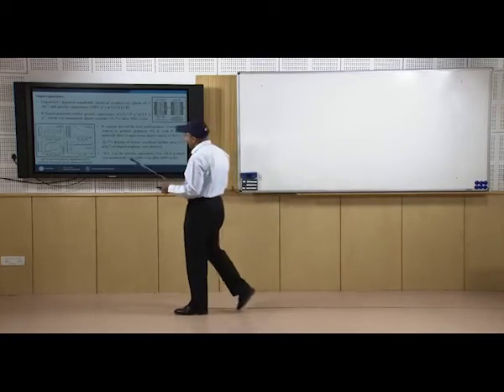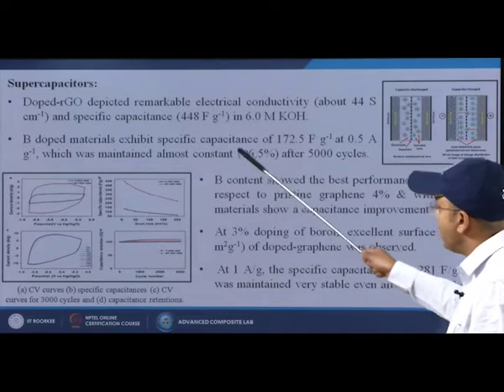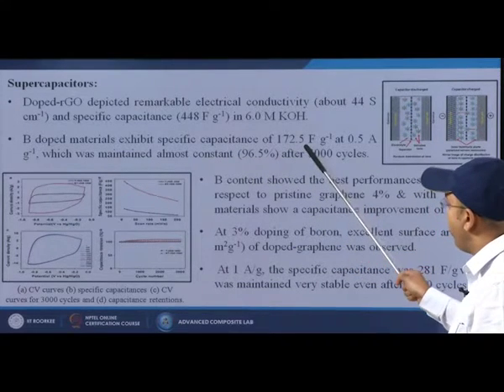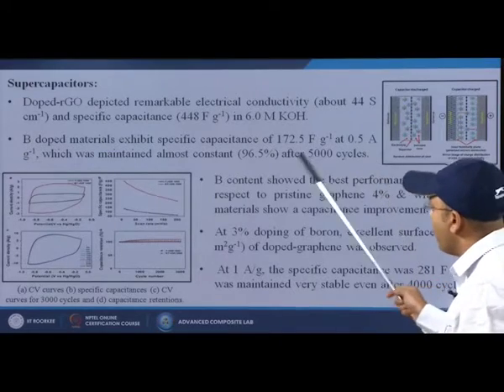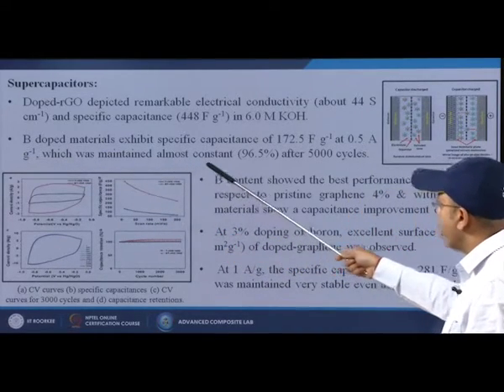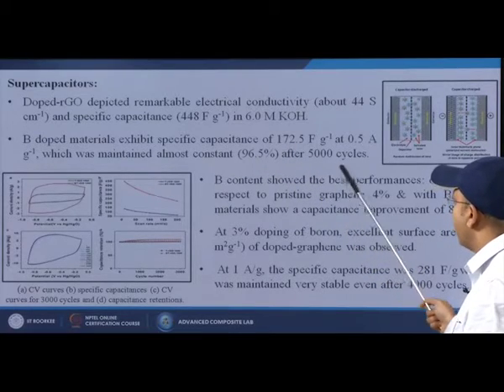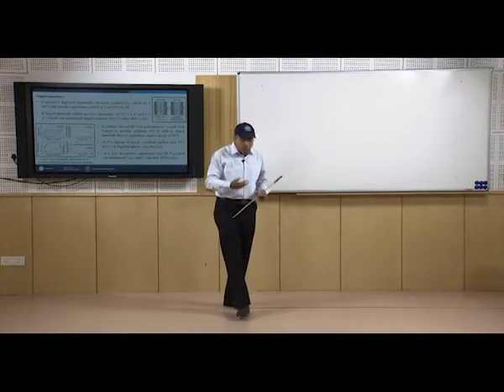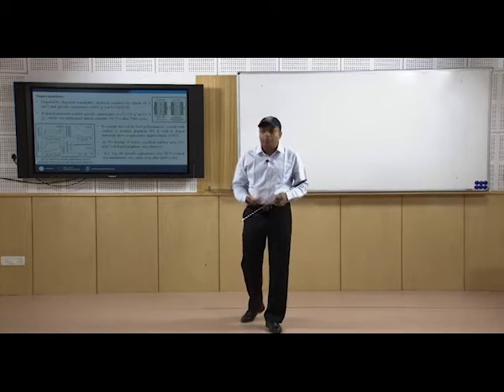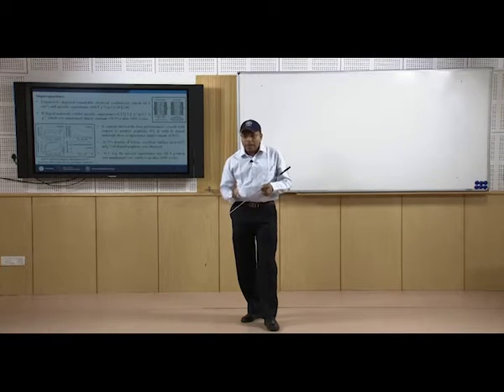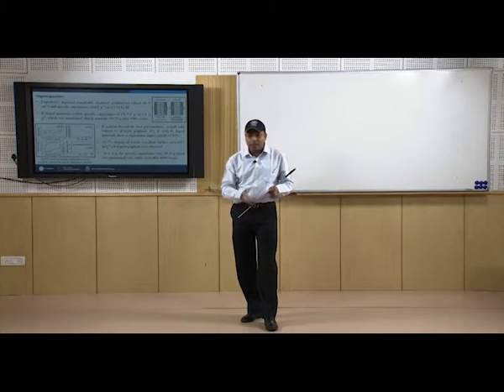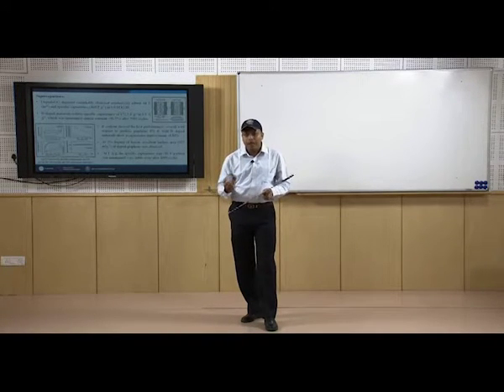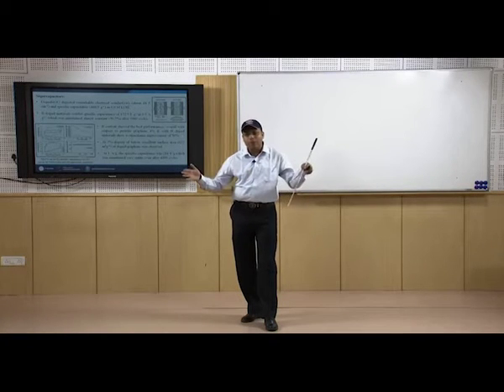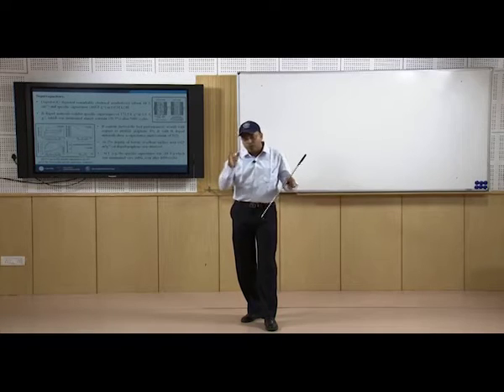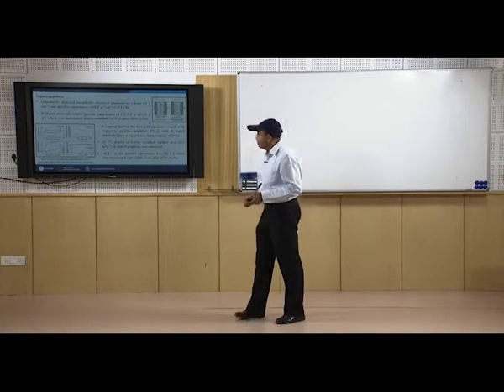So here also we can see that boron doped materials exhibit a specific capacitance of 172.5 farad per gram at 0.5 ampere per gram, which was maintained almost constant, 96.5%, after 5000 cycles. That means the longevity, or the life, of that particular material has been enhanced. When I am charging and discharging that material several times, the capacity of the material still remains the same. That means the battery life, or the supercapacitor life, is increasing, so that I can use this material for a longer period.